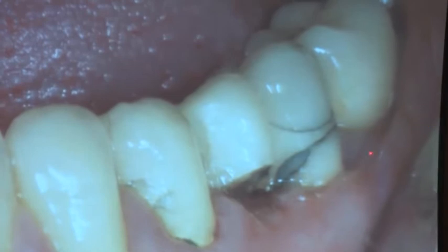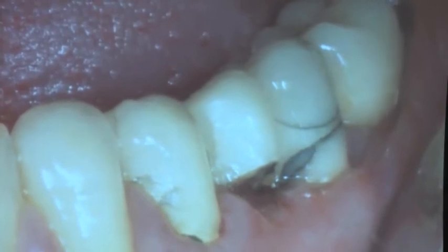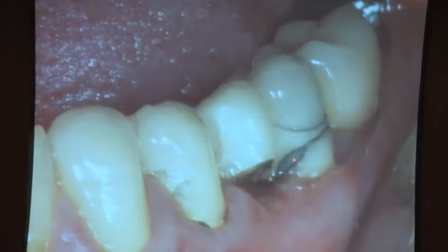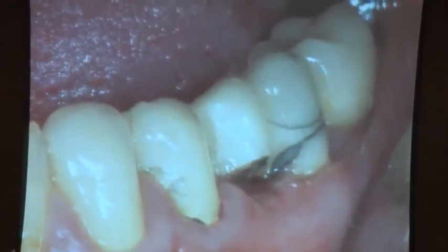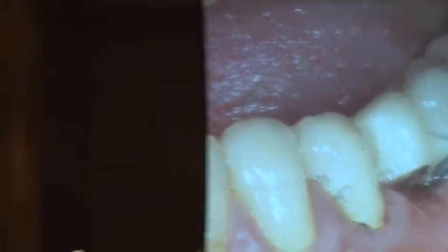Chip off? Yes, but what's this black stuff? The gray one is the metal, right? But what's between the metal and the opaque? What do you think is in between? I think cement. No, the cement is underneath. It's like oxide. Normally you do an oxide firing, then sandblasting, depending on which metal you're using, to remove these oxides. When you do the oxide firing, you sandblast, then you steam clean it, then you apply your opaque.